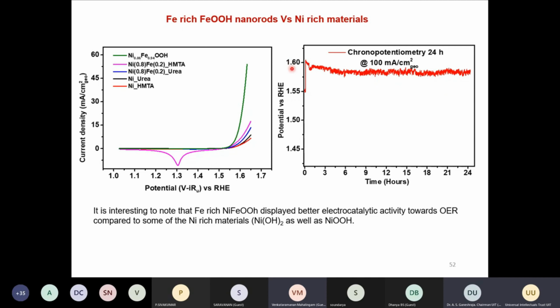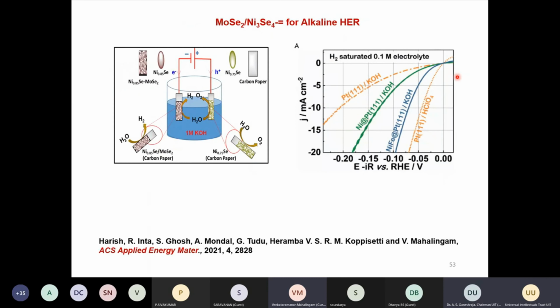So we also did the chronopotentiometry to understand the electrochemical stability of this catalyst for 24 hours, and found that initially there is a slight decrease in the potential, and then it basically maintains this. So in the next couple of minutes, I will show you one example of an interface material which is used for the alkaline hydrogen evolution.